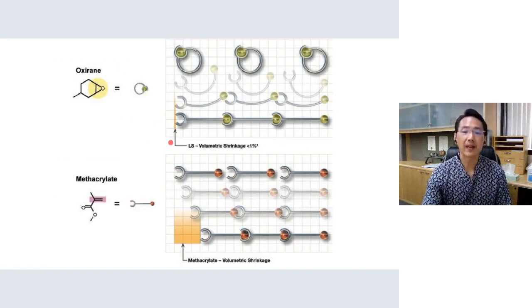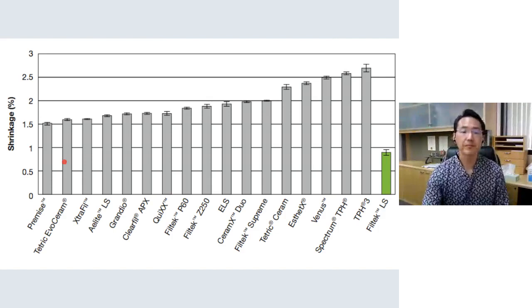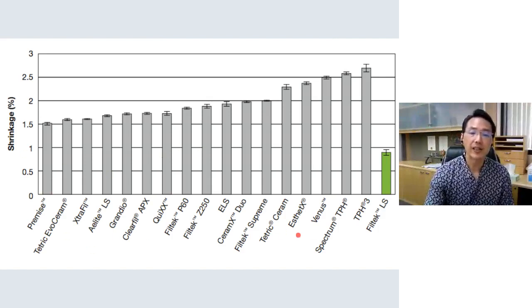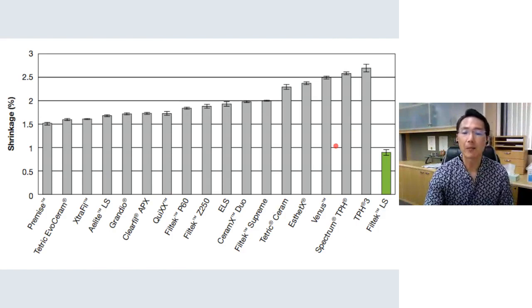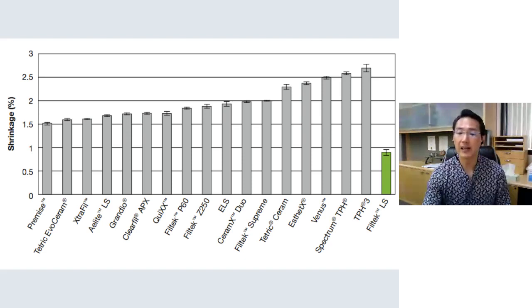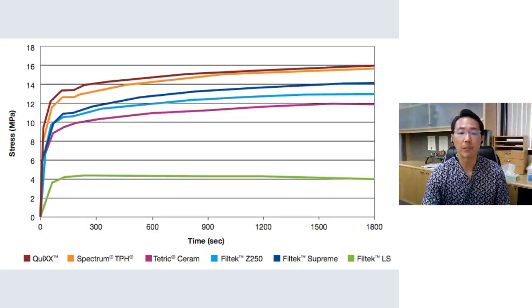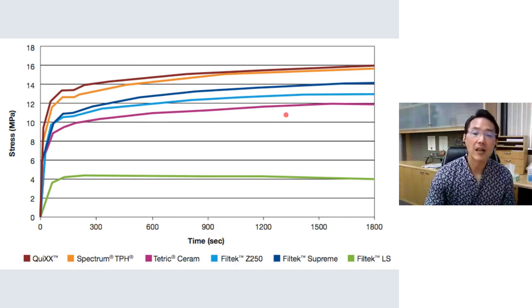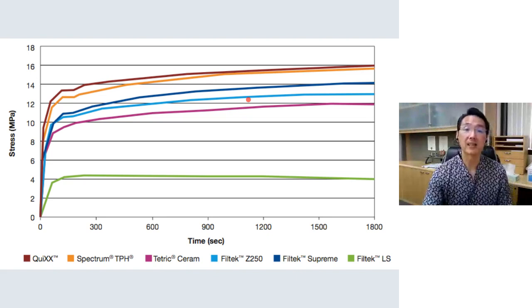So here's a schematic from their brochure. You have the oxirane here that expands and connects to the neighboring one and reduces the shrinkage. While with a methacrylate, you have the free space that reduces when you connect the neighboring monomers together. So here is the percent shrinkage of the different composites. I can't point it out because I've got this stupid bar here. But the last one here, I think, is the LS, and the shrinkage percentage is less than 1%. You can see their shrinkage stress. This one they have at 4 megapascals, and the other composites that they measured, again, this is a company brochure, vary anywhere from 12 to 16 megapascals, which is still very high.